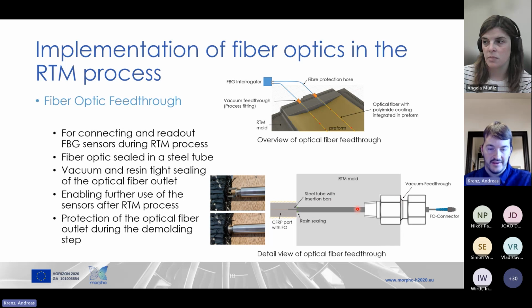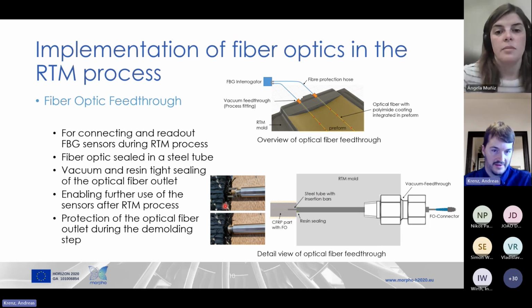And so we have the solution of leading out the fibers in the steel tube and sealing it inside the steel tube and outside the steel tube at the mold. And the idea was that the steel tubes remain after manufacturing as part of the CFRP panel on the edges of the CFRP panel. And so we had some additional insertion bars on one end of the steel tube, which should be inserted into the edge areas of the preform.